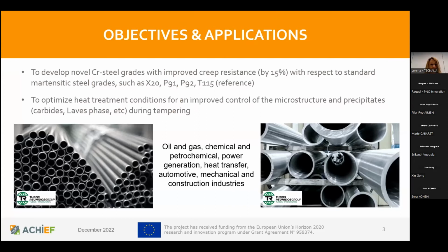The first objective is to develop novel chromium steel grades with improved creep resistance with respect to standard martensitic steel grades, those commercial ones, such as X20, P91, P92, and the reference steel finally selected in the project, which is T115. The second objective is to optimize heat treatment conditions for an improved control of the microstructure and precipitates that can be formed, especially during the stage of tempering. There below, you have an example of the products offered by Tubos Reunidos for oil and gas, chemical and petrochemical, power generation, heat transfer, automotive, mechanical, and construction industries.